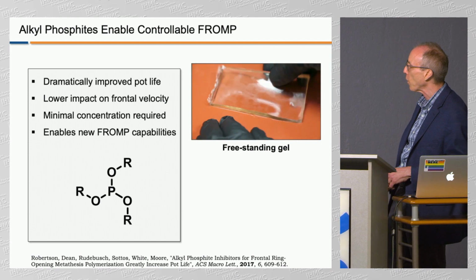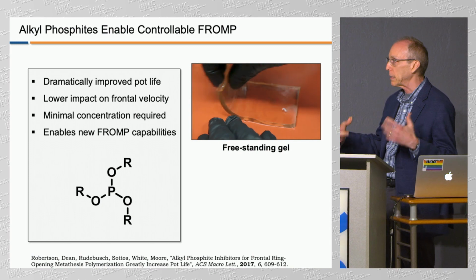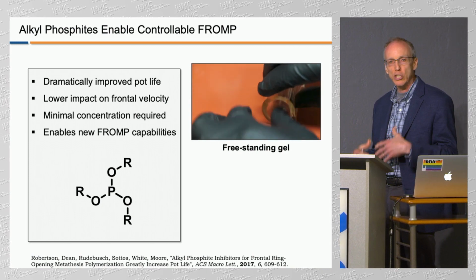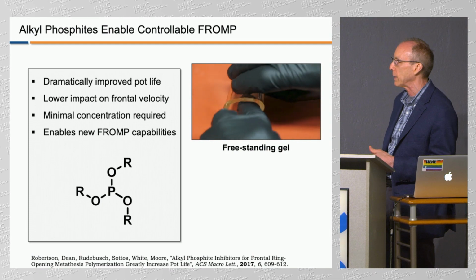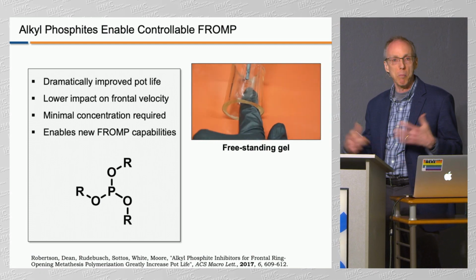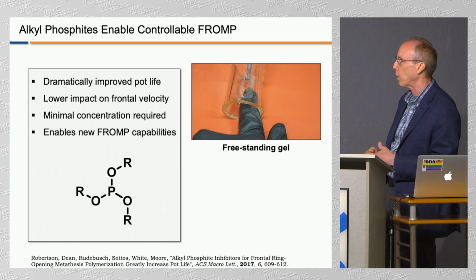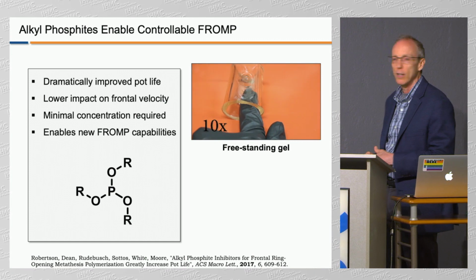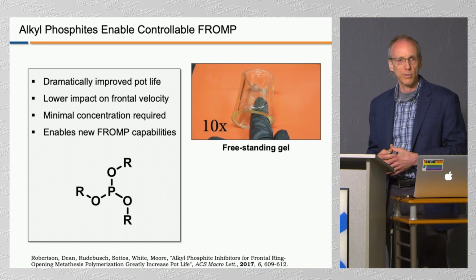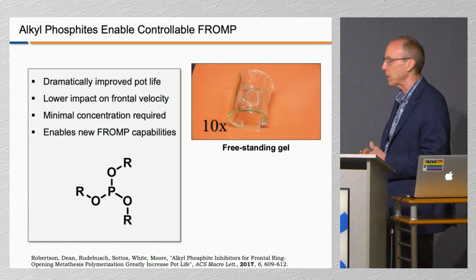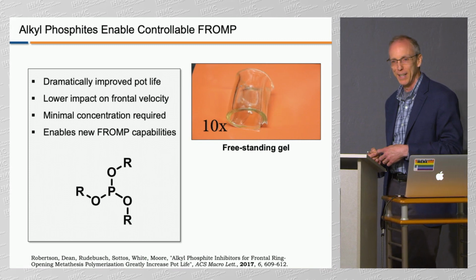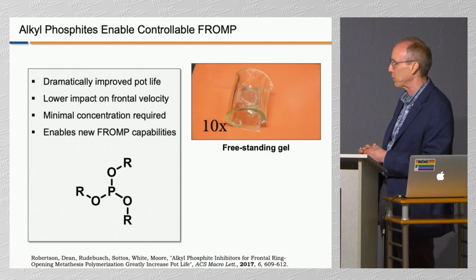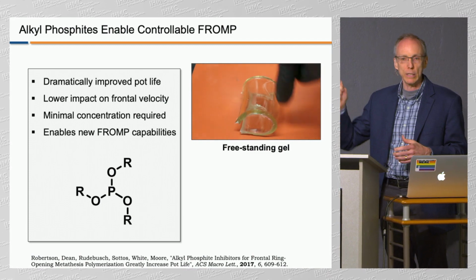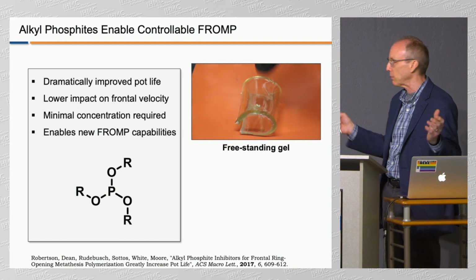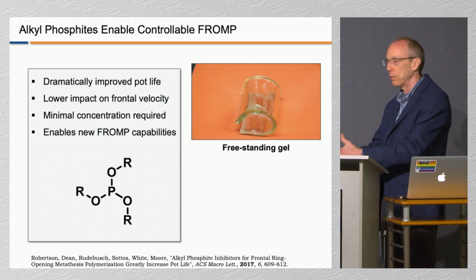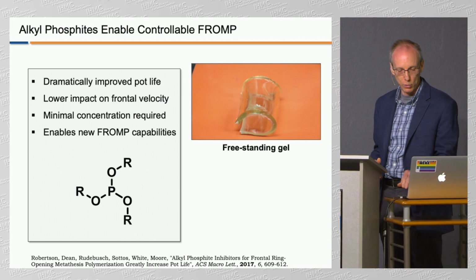We're all familiar with gels, gelatin, and that's what happens to this. And so Ian discovered he could take that gel, which is largely still that liquid monomer, but now it's been gelled to a point where he can mold it and bend it and shape it. And there's still enough liquid monomer in that gel, just like gelatin has a lot of water, that he can take a soldering iron and then trigger that gel to begin to undergo the rest of the polymerization. The rest of the monomer can polymerize. He had to get his finger out of there because it's getting kind of hot as that frontal ring opening metathesis polymerization takes place. But now Ian could literally jump on top of this and it wouldn't deform at all. So he took what was a liquid, transformed it into a gel, and then now into a really structurally sound material.